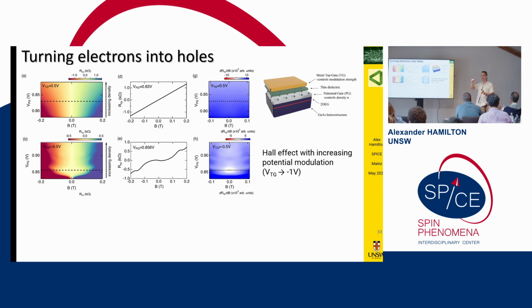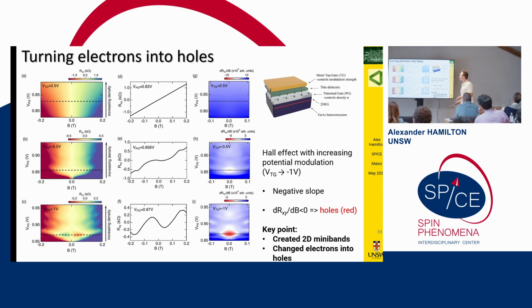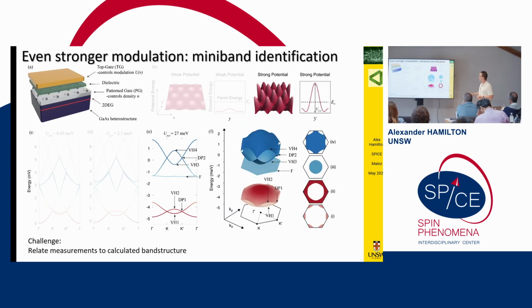Now what I'm going to do is turn up the modulation a little bit. And when I turn up the modulation, my Hall voltage, instead of being a straight line as a function of magnetic field, kind of goes completely flat around zero magnetic field. And if I turn up the modulation a little bit more, the Hall voltage actually changes sign around zero magnetic field. That means here I had electrons. Here, this Hall voltage, it's changed sign. I've changed my electrons into holes. And this is exactly what I expect. Down here, I have electrons. Up here, I should have holes.